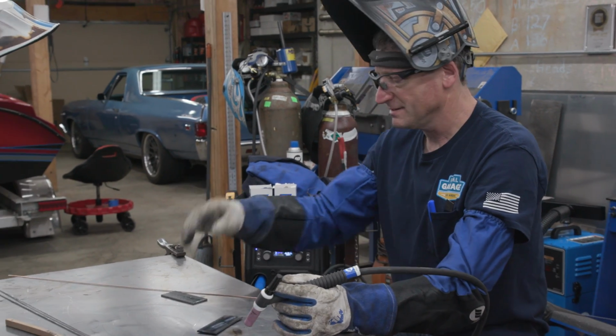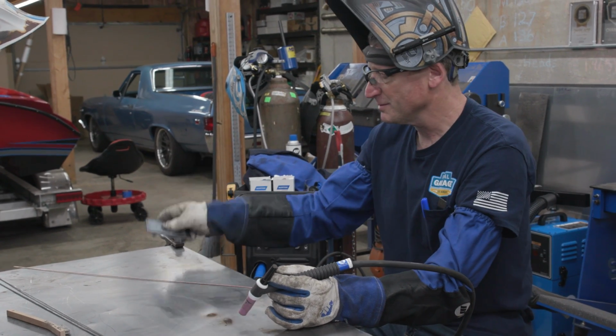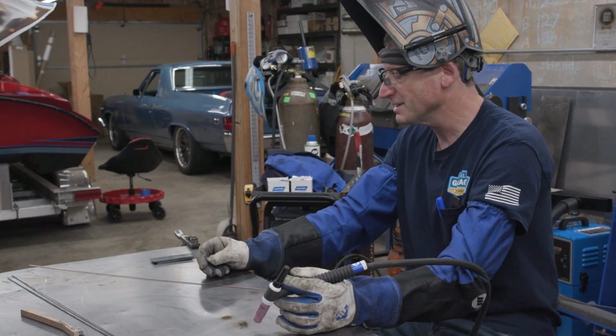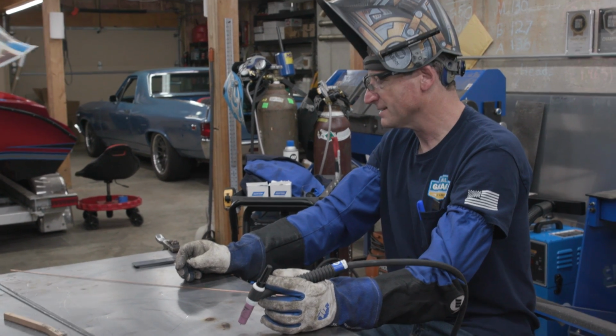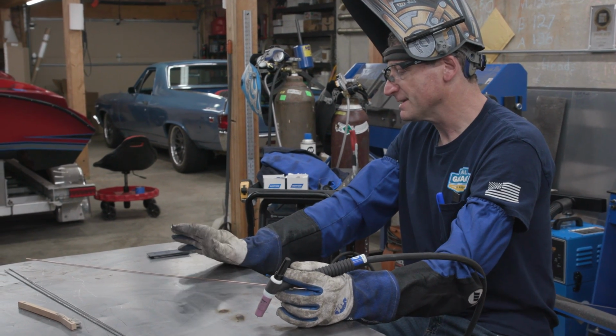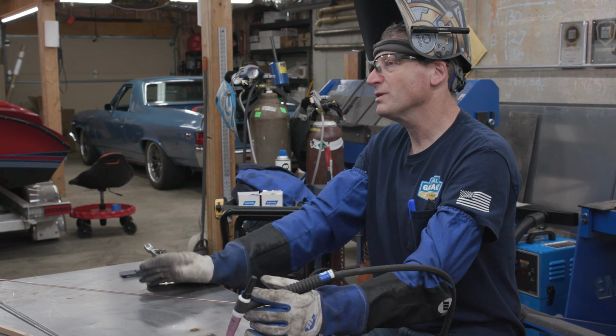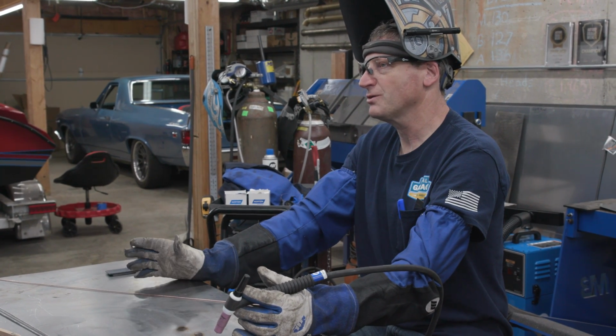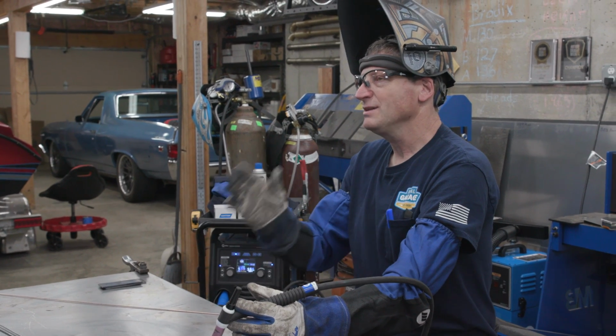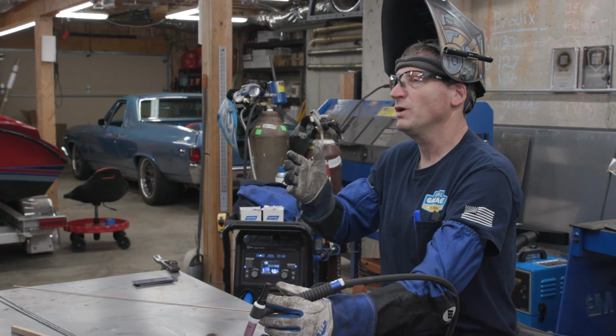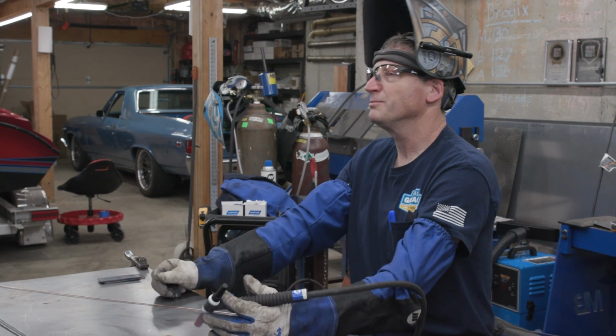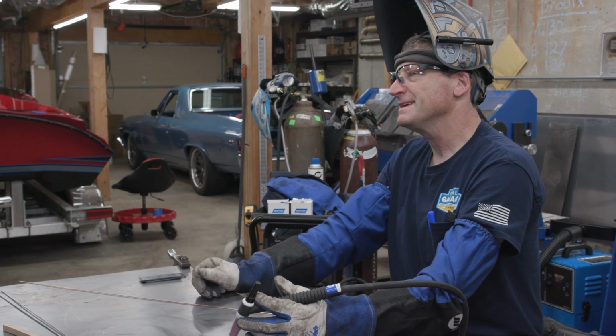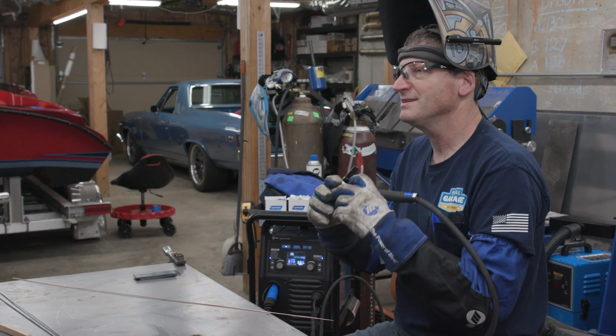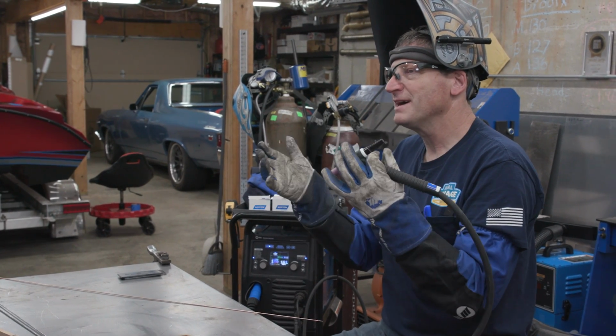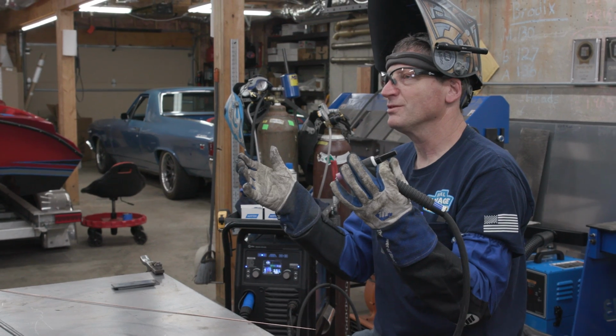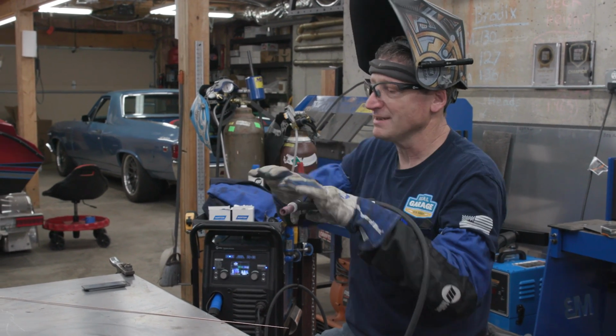But yeah, let's move on to the Dynasty, because the DC, that's pretty much all you can do on that. Your pulse range is fairly limited, up to 150 max, which is great because it still agitates the weld puddle. So if you're working with two dissimilar steels, let's say chrome moly to mild steel, adding the pulse at a high pulse rate actually agitates the weld puddle, and it'll give you a better grain structure and a stronger weld bead. Rather than just a straight constant DC where you're adding filler metal, imagine a bag full of different sized marbles, and then you shake the crap out of the bag, they start to line up.